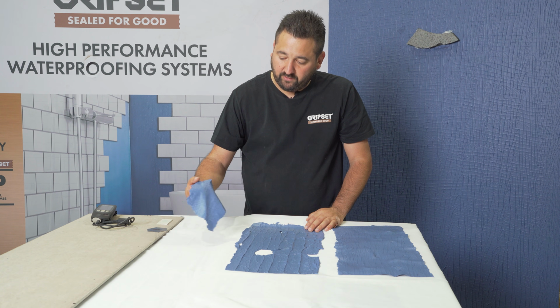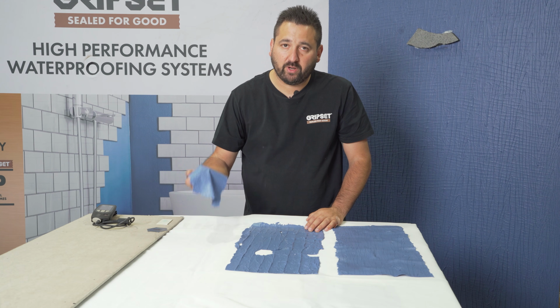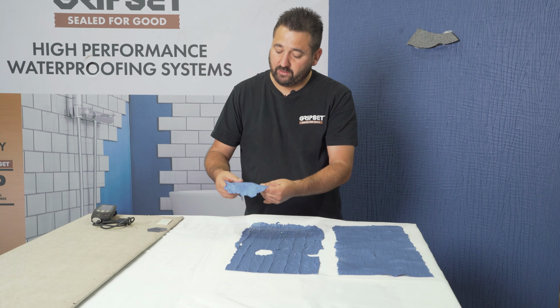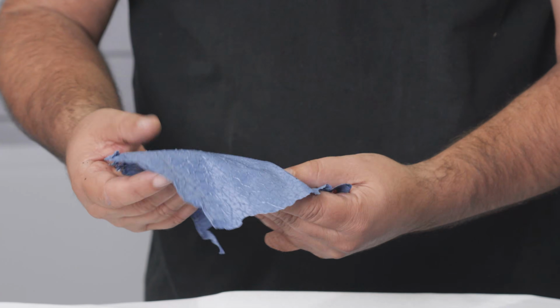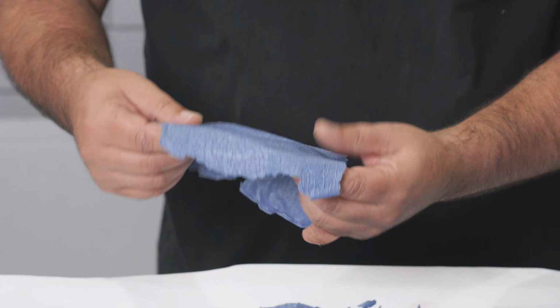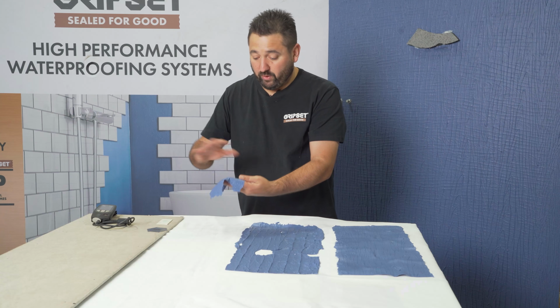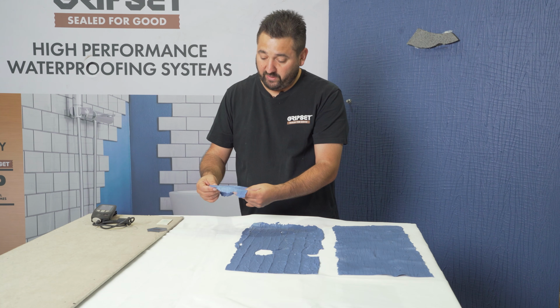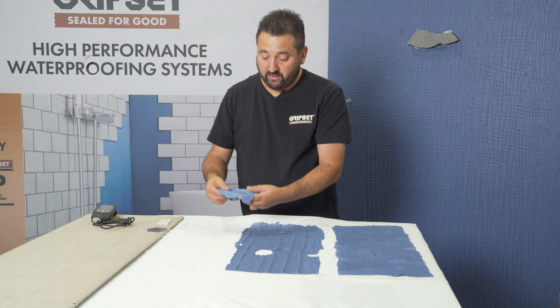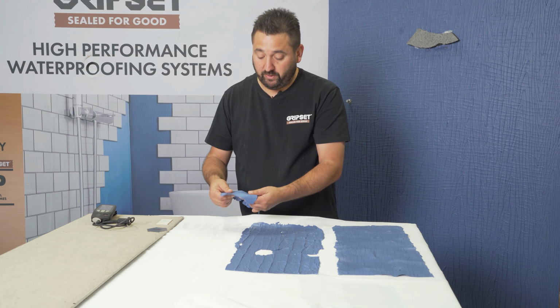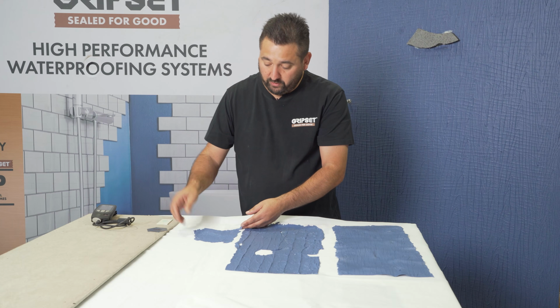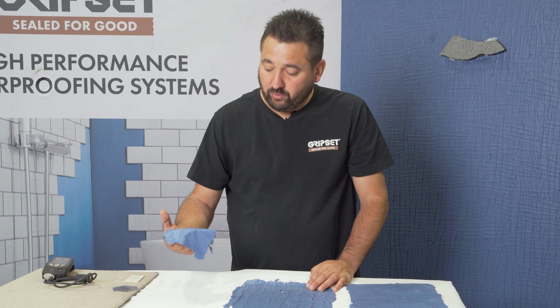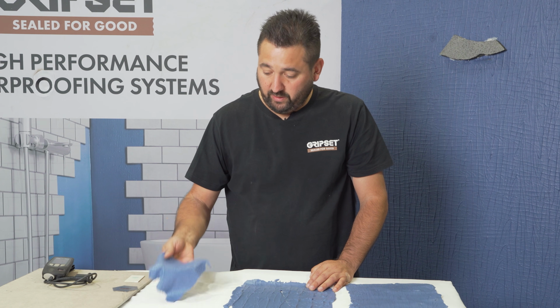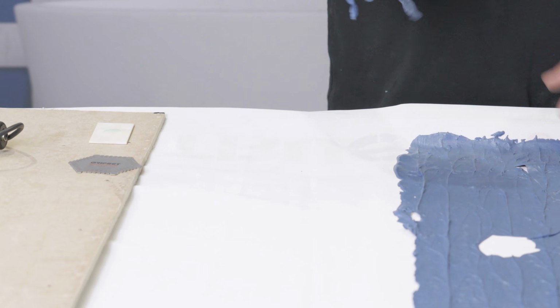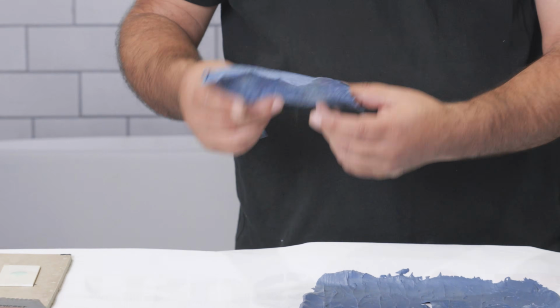And this is precisely the risk of when you under apply a membrane, right? So if you're not getting it to the right thickness, it's not going to be strong enough. It's not going to reach full adhesion. It's not going to have the right water vapor transmission properties. It's not going to have the right elongation properties. It's not going to have the right tensile strength properties. So pretty much across the board, it will not perform as per the assurances that we provide in the technical data sheet. So this is probably one of the worst case scenarios, is under applying the membrane.